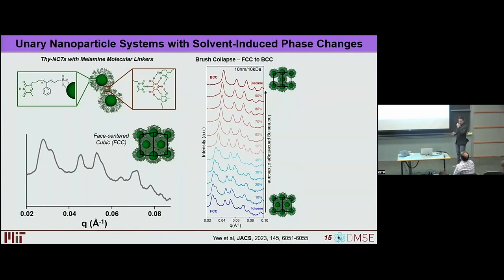And so we saw a couple of really great talks yesterday explaining why this happens, and so I don't want to go through that in more detail. But the basic take-home from the talks from yesterday was that you go from an FCC to a BCC case because as you're compressing the lattice, there's an entropy penalty on all of these polymer chains. In the FCC case, they are as maximally dense as possible, but as you compress it, the configurational entropy of the polymer chains gets less and less, and at a certain point, they flip to the slightly less dense BCC case so the polymers can spread out a little bit and regain some of that configurational entropy.